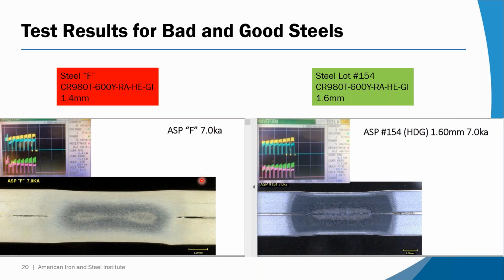I basically had provided a written response saying that in our study we did not summarize the total number of cracks that we have seen, but we do have another LME study being done in a different task where we actually do summarize the number of cracks we observe. It does factor into what we call a cracking index, but not in this particular study. Right. What we do preserve is the visual external view of the weld, so you can count different types of cracks. But unfortunately, when you do a cross section like I'm showing here, you have to choose from the external view, looking at the weld, what plane you're going to section. And once you've done that, you're not going to be able to measure crack depths in any other plane because you've kind of destroyed the part.